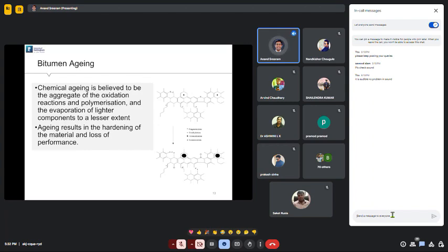However, when oxidation happens, oxygen enters these molecules and makes it more and more stiff. And as a stiff material, it is more brittle, it's more prone to cracking, both in terms of fatigue cracking, long-term cracking, as well as low temperature cracking. So the reason our pavement deteriorates over time is mainly because the original material is not good anymore. It's weak and it's more brittle.